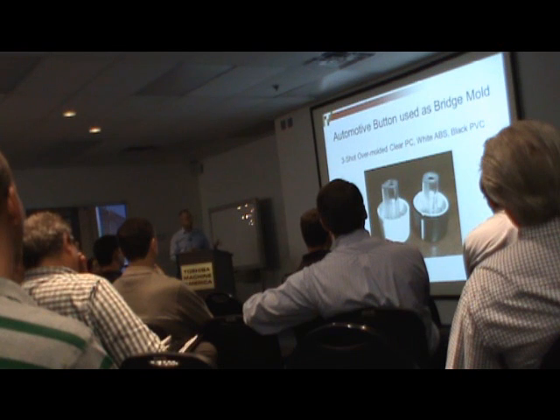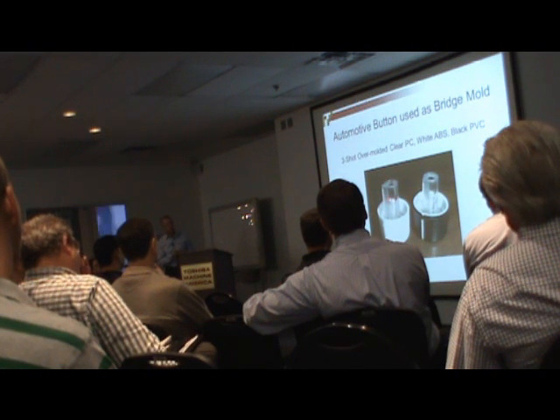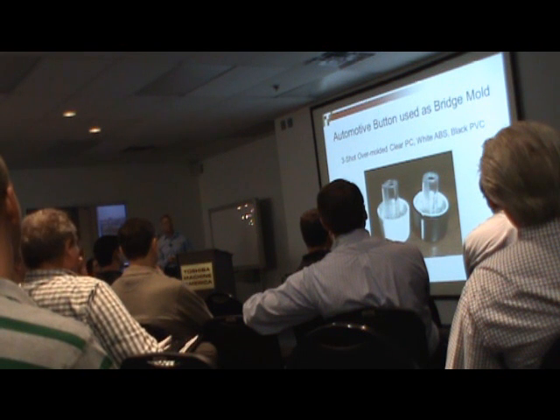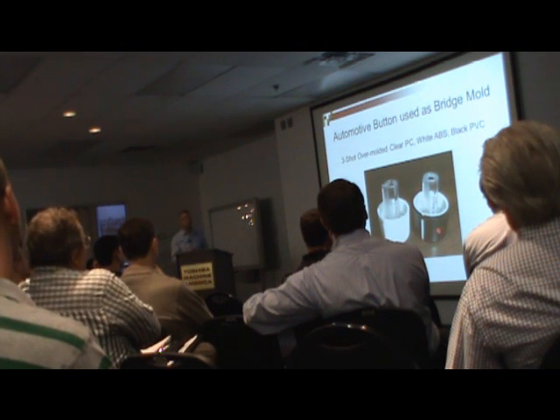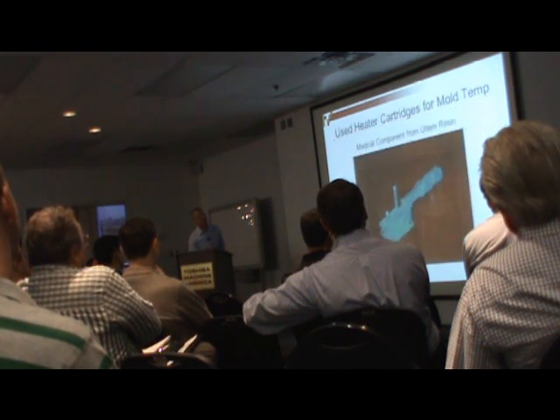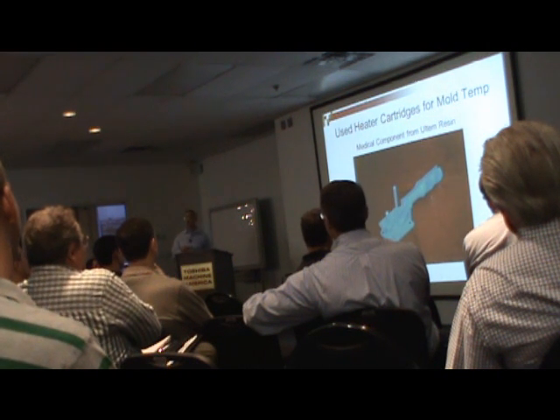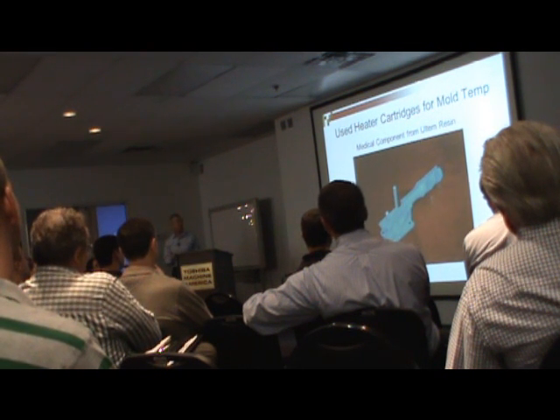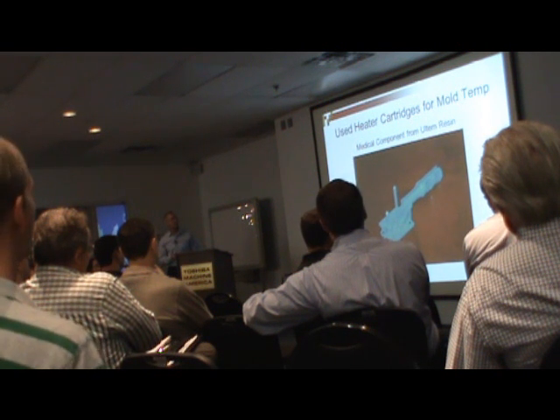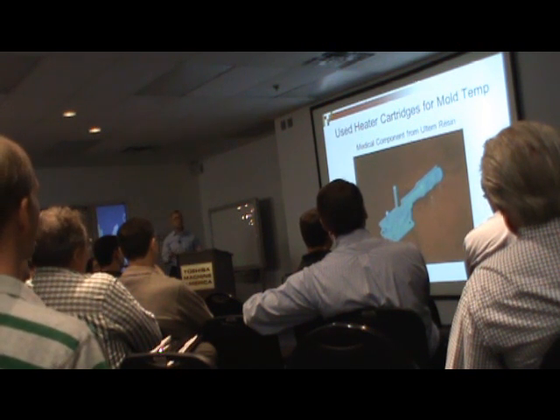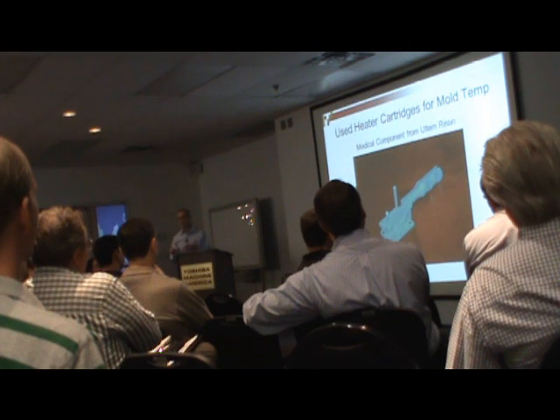We run some 2 and 3 shots. The first shot is a clear PC, the white is the ABS indicator, and then the third shot is a soft PVC. To date, we ran about 120,000 of those parts total. Those are actually single cavity tools. This is an Ultem material. What we do is use heater cartridges to bring it up to temp. We do not use oil.